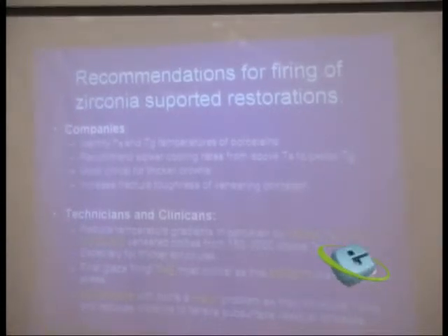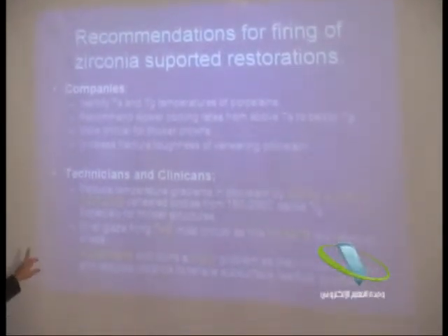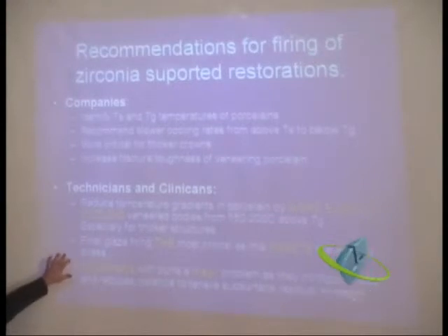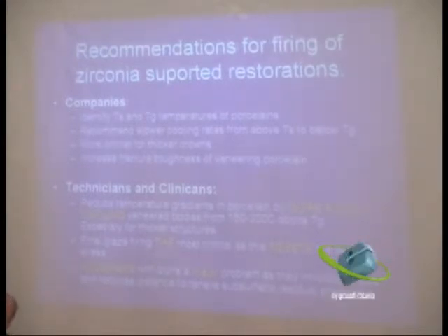The role of the clinicians and technicians. Ask your technician to slow down the cooling rate, particularly for zirconia. If you don't know the TG or the TS, then from about 150 to 200 degrees C above the TG, you should slow down, particularly for thicker systems. The critical process is the final glaze. The final glaze cycle is the one that resets the stress structure in your system, so that is the one where you really have to slow down the cooling. Intermediate firings are not so important because you're going to heat up again and relax the stresses, but the final glaze firing is the most critical.